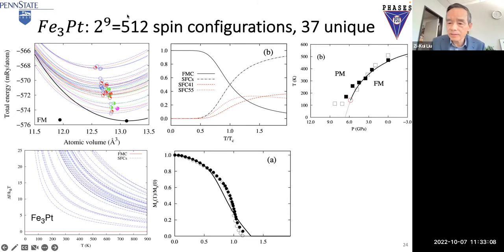And you can fix that at different temperatures and pressures, because you do different pressures now. You get an E-V curve for each pressure. You find that against temperature and pressure, the pressure is decreasing, because minus PV is our potential in thermodynamics. Again, the symbols are from experiments and lines from prediction. Above here is the second order transition, below there is the first order. The first order seems to have a large error, but the second order transition is beautifully predicted, including this critical point.